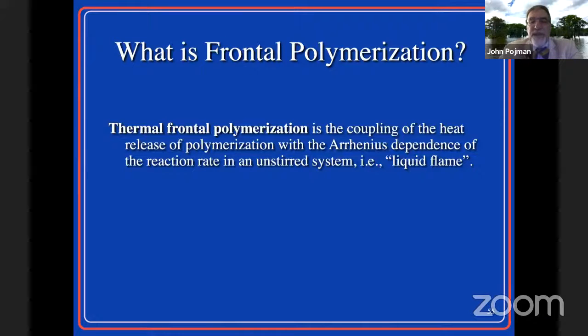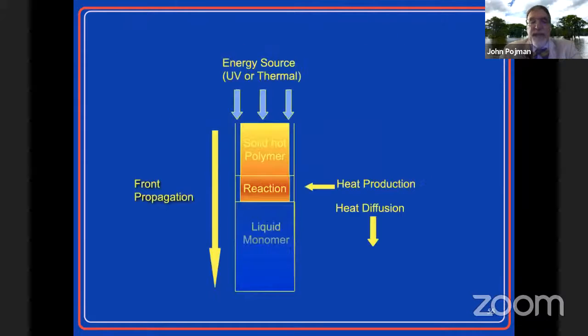But let me switch to another process called frontal polymerization. So it's a coupling of the heat release of a polymerization with the Arrhenius dependence of the reaction rate. Very simple experiments to perform. So you can think about it, it's very similar to a burning cigarette or burning cigar. You have a reaction that produces heat. The heat spreads. That causes more chemical reaction, which releases more heat. And you have a self-propagating front.